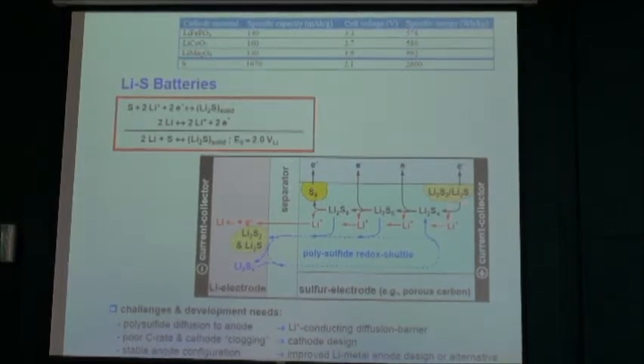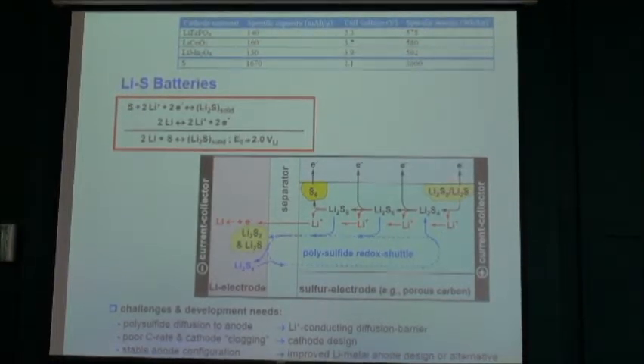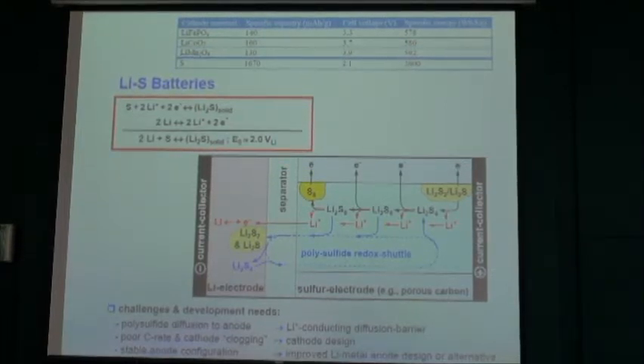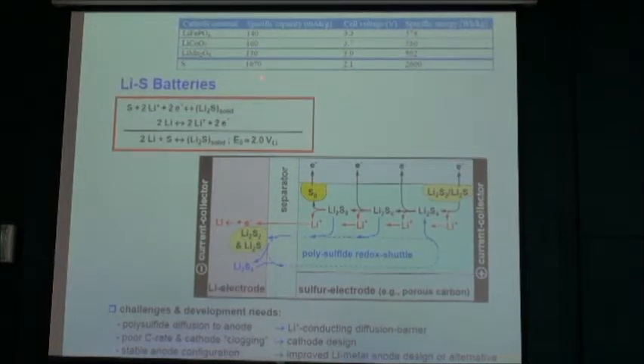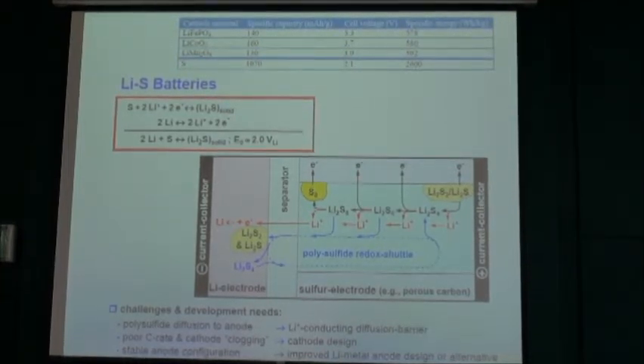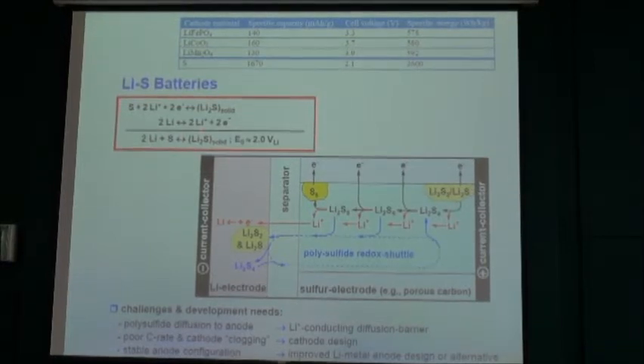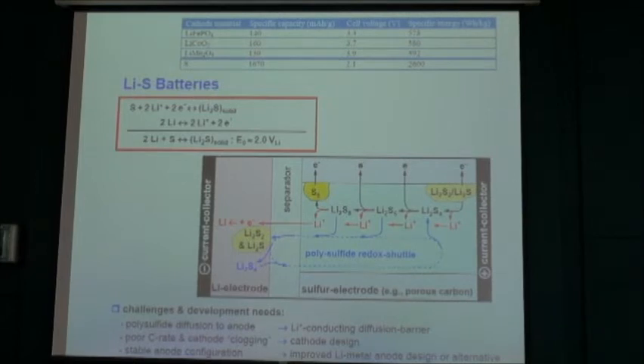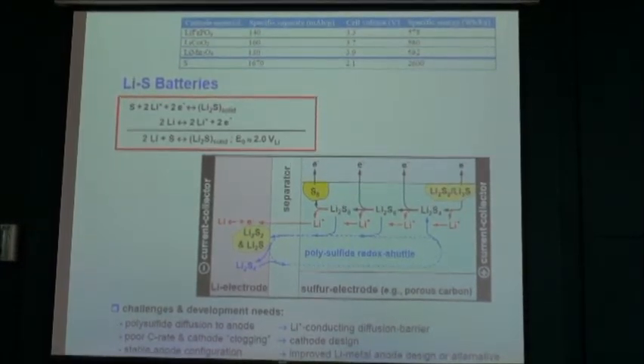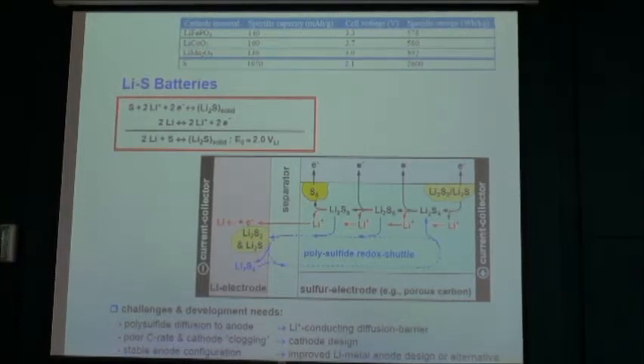Finally it becomes Li2S or Li2S2, but it doesn't go directly from here to here. It goes through intermediates we call polysulfides: Li2S8, Li2S6, Li2S4, then eventually the final Li2S. Li2S gives you a voltage of 2, and the capacity is about 1670. The problem is these polysulfides dissolve in the electrolyte. The final product, Li2S, is stable, but the polysulfides dissolve in electrolytes, so you cannot recycle them. Polysulfide dissolution is the biggest problem.